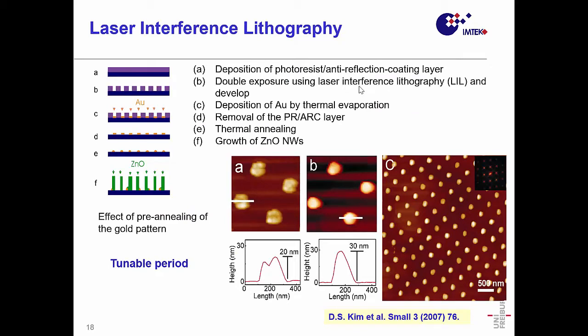Another method would be using laser interference lithography. For that, you need a UV laser. You spread that through a pinhole, widen it, and then make an interference pattern, and then you are able to do lithography on whole wafers, depending on your system. Again, take into account that your substrate might reflect the laser, so you need to take care of that with an anti-reflecting coating.